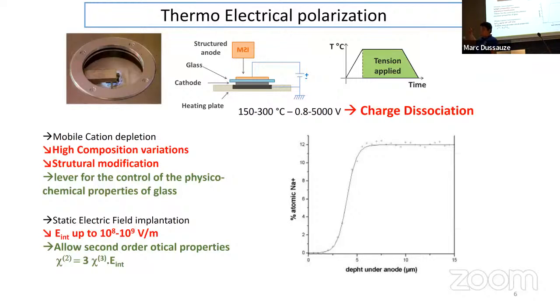And the second one is the induced space charge that you can obtain inside this layer. So you can have a static field inside the glass that can be extremely high, as you can see, up to the gigavolt per meter. And this allows different kinds of electrical functionality, but also second order optical response. So please try to remember these two levers that we can use to induce new functionality in different kinds of glass. So changing compositions first, and then this static field that we put inside the glass matrix, which is the second lever to get new functionality.